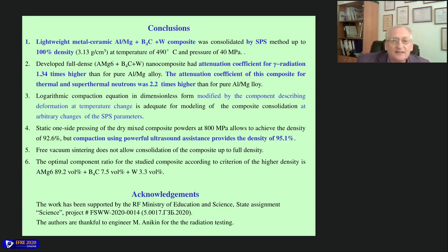The developed full dense composite had an attenuation coefficient for gamma rays and for thermal and super thermal neutrons higher than for pure aluminum magnesium alloy. The logarithm compaction equation in dimensionless form, modified by the component describing the deformation at temperature change, was adequate for modeling of the composite consolidation at arbitrary changes of the spark plasma sintering parameters. At the same time, static one-side pressing of the dry mixed composite powder